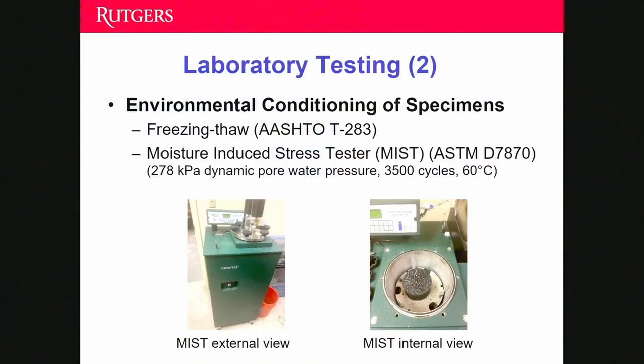before doing the mechanical testing, we put the specimens under 2 different environments related to moisture. The first is freeze-thaw. Basically we put samples at -20 degrees C for 24 hours, and then put them in a 60 degrees C water bath for another 24 hours, and then we do the test.